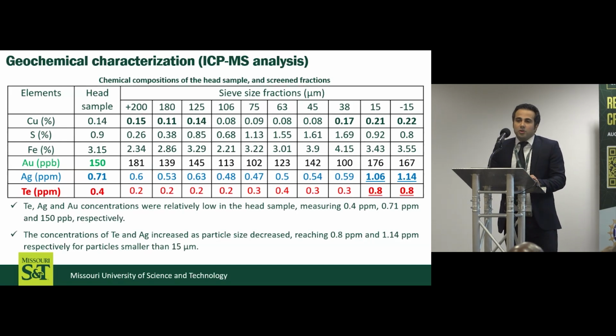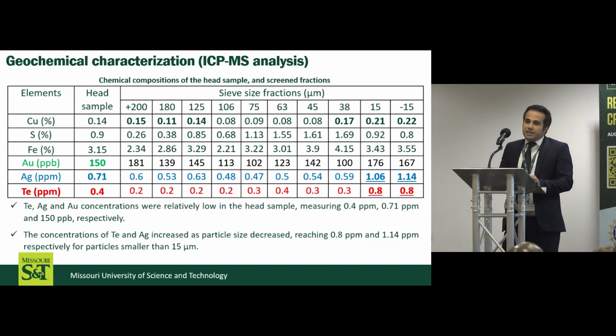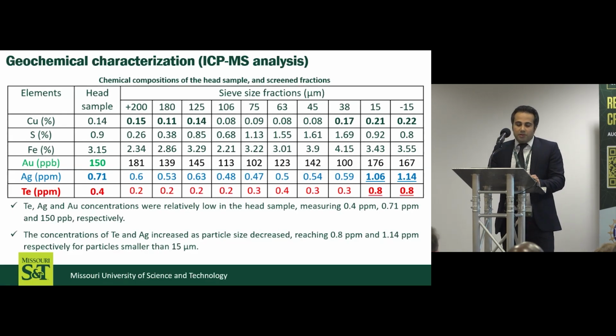There were noticeable variations in the chemical composition of the head sample in different size fractions. Copper concentrations were high in both coarse and fine particles, showing that these particles were transferred to the flotation tailings because of the poor liberation of coarse particles and low floatability of very fine particles. The concentrations of tellurium and silver increased as particle size decreased, reaching 0.8 ppm and 1.14 ppm, respectively, for particles smaller than 15 micron.